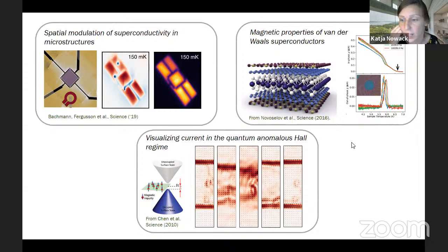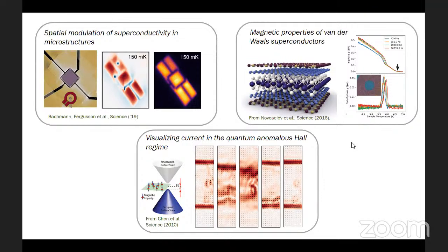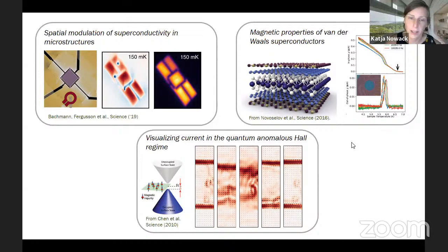our squids actually have a lot of topography. If you were to look at them from the side, they have a lot of terraces and steps and whatnot. And so if I keep all that extra circuitry, there's no way for me to bring the sensitive area closer to the sample than maybe within 300-400 nanometers.